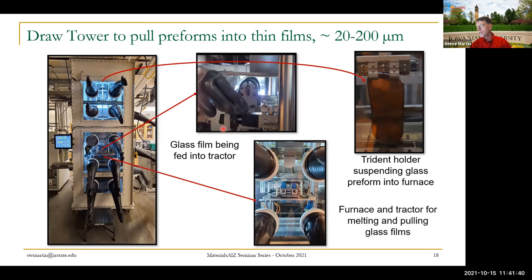And then eventually, again, these are micron thick films. So what you're seeing, you're looking right through one of these films. There's a film, you barely see, there's a little bit of reflection right there. You can see we're pulling a 20 micron thick film of this glass in that bottom picture.